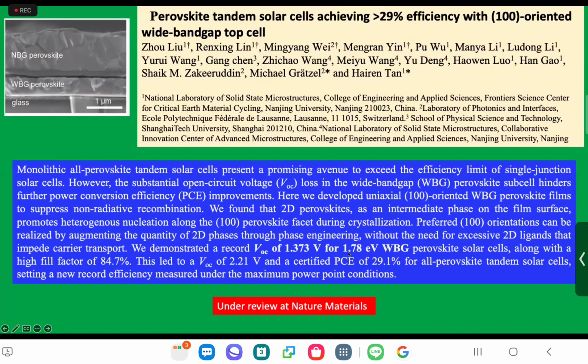the amazing result we got by this simple treatment, okay, was that the VOC went up to 1.373. That's very hard to get for 1.78. So we're getting 400 millivolt deficit, okay? Now, I want to point out it's a little bit better than what Tom Miyasaka had shown, okay?